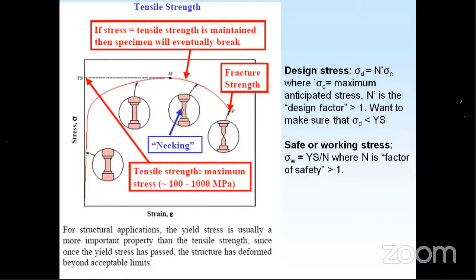Actually, austenitic stainless steels, whatever we normally use, have a tensile strength of 500 to 550 MPa, and YS is 200 MPa. That means UTS is nearly double the YS. But in the case of maraging steel, it is 1725 MPa YS and 1750 MPa UTS. That means it is very, very critical.